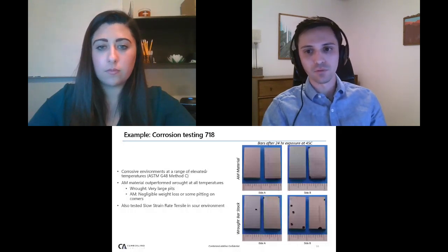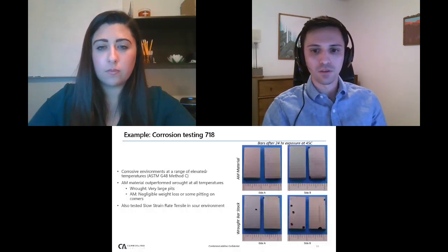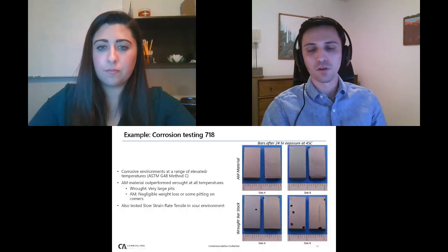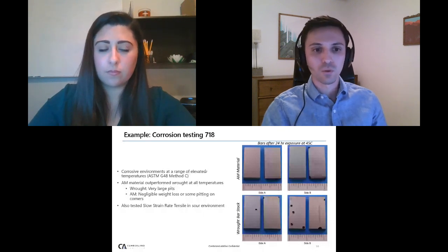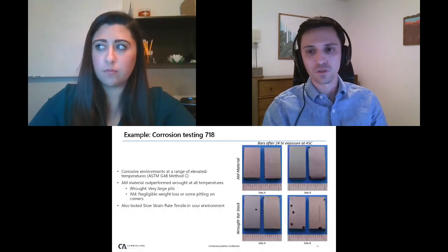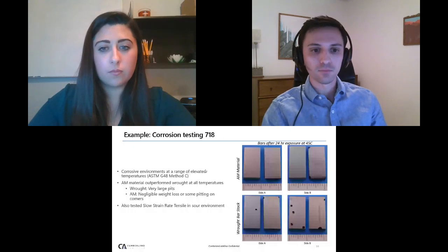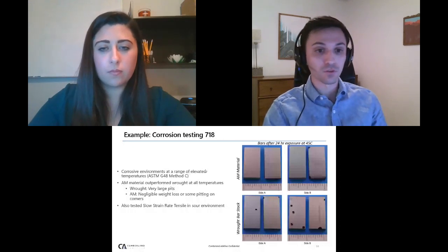In this example, 45C, you can see that the raw material has large pits all over, and when we're weighing the samples, there's weight loss, the obvious loss of material from corrosion, whereas the AM material had either negligible weight loss, very little, or maybe some corrosion starting to happen at the corners. We've also tested slow strain rate in a sour environment with similar results.